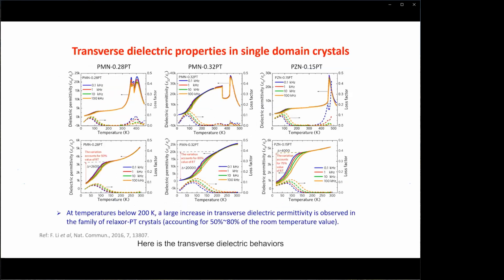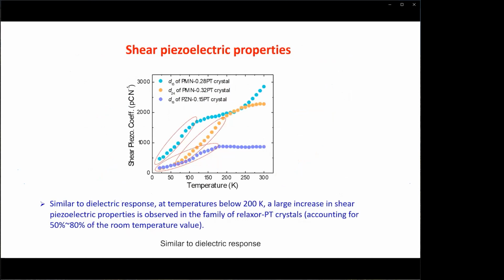Here are the transverse dielectric behaviors in single domain crystals. We can see that there is a large increase of transverse dielectric permittivity at low temperatures. This variation is about 50% to 80% of room temperature values. Furthermore, dielectric relaxation is clearly observed in these figures. Here we can see that the loss factor shows a peak value in each figure, and the peak temperature increases with increasing frequency. Similar to dielectric response, shear piezoelectric properties were also found to greatly increase with increasing temperature from 50 Kelvin to 200 Kelvin.